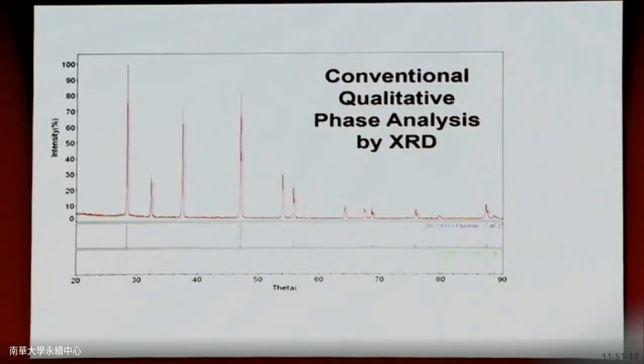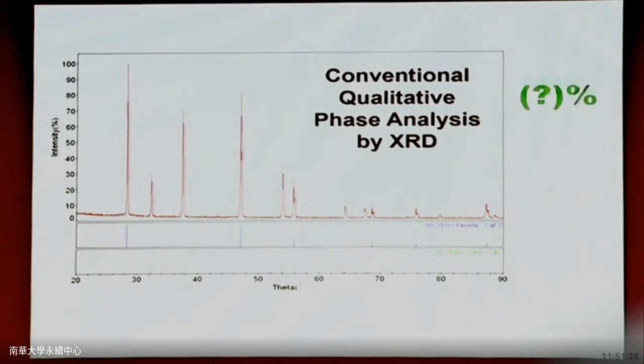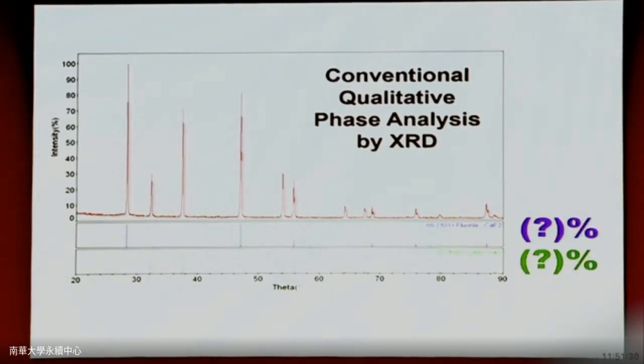So this is a typical X-ray diffraction that you can put a material in there, it will give you a pattern, and you just use the standard pattern A and B to fit it. Everybody can do it pretty much in the area. But if I ask how much percent A and B, 99% of people do not do that because they don't know this quantitative, and they don't know this conventional qualitative analysis of X-ray can be quantitative.